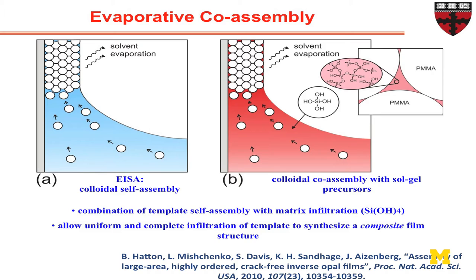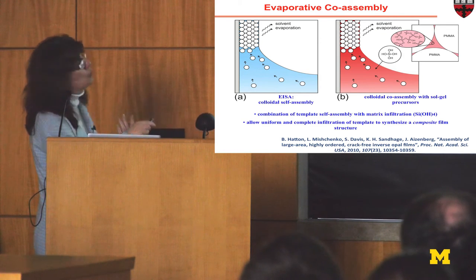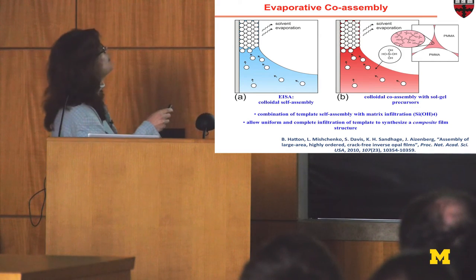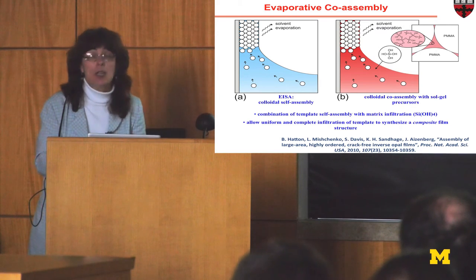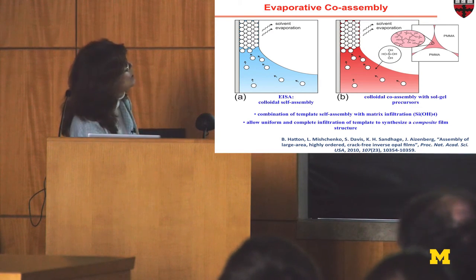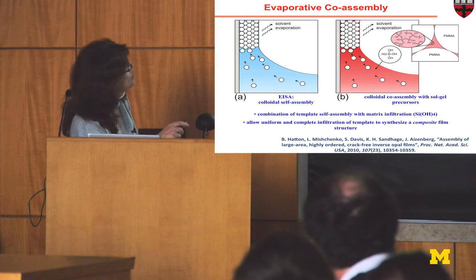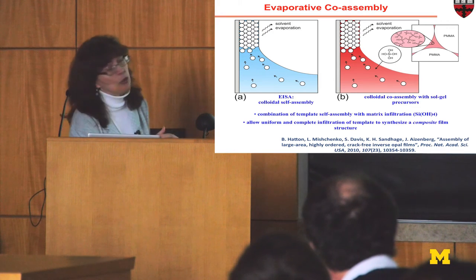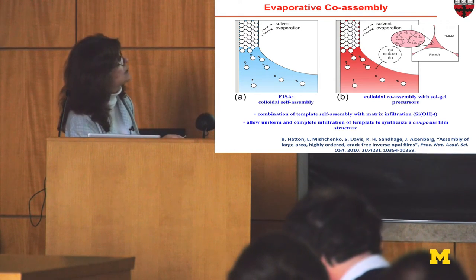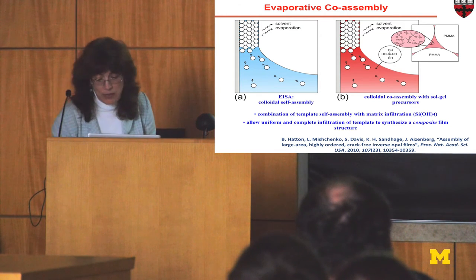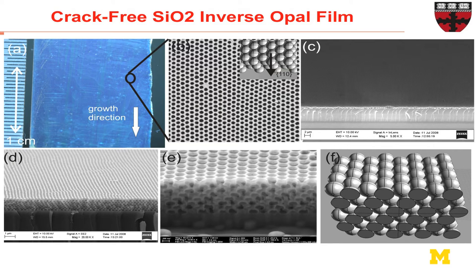So at a certain moment we decided to try to do it, and being lazy, instead of the traditional approach to colloidal assembly, to make inverse structures, what is generally done is you use solvents, your colloids are assembling, then the solvents evaporate, then you infiltrate it with sol gel solution, then you burn away your colloidal particles, and you end up with inverse structure. So we were lazy, we didn't want to do it in so many steps, so we assemble our colloids not from a solvent that goes away, but in fact directly from sol gel solution. So what happens then is not only that it's faster, but it also provides a way to avoid cracking and the problems in colloidal films, because sol gel,